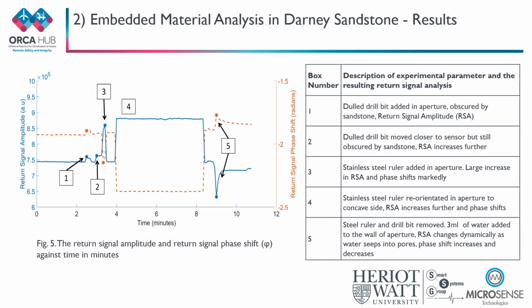Figure 5 displays the return signal amplitude on the left y-axis and the return signal phase shift on the right y-axis. The main reflection, or peak, from each frequency sweep was then recorded and is now displayed on the graph as a blue solid line. What we can identify is on the lead up to marker 1 at approximately 2.5 minutes, the baseline measurement for the Darney sandstone and aperture is being established.